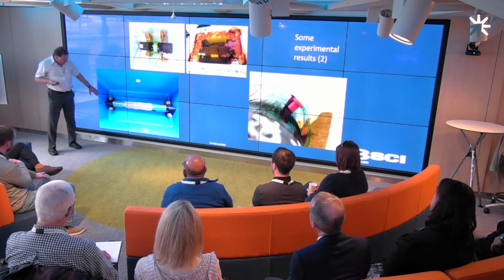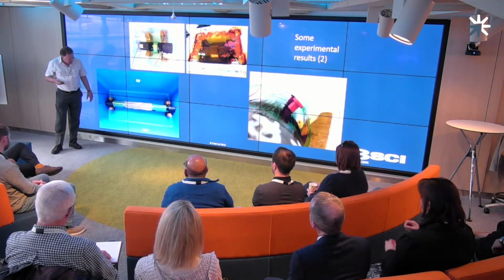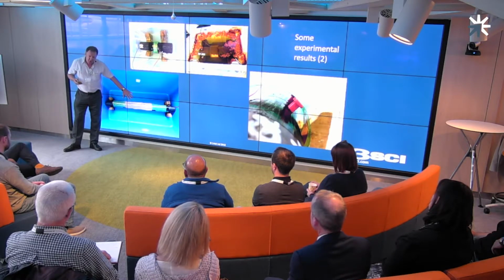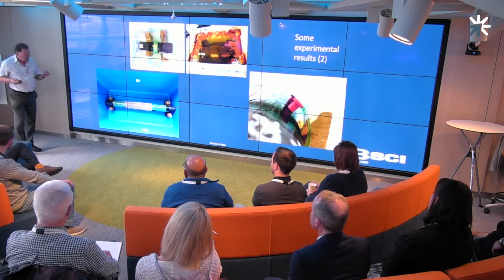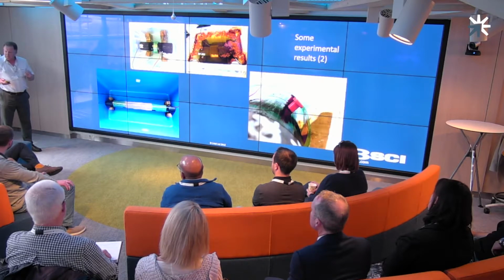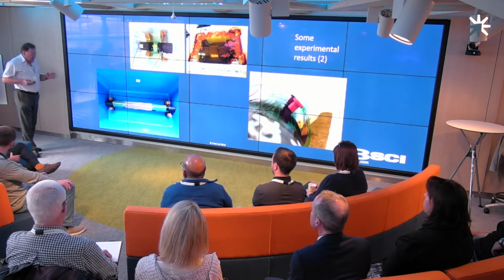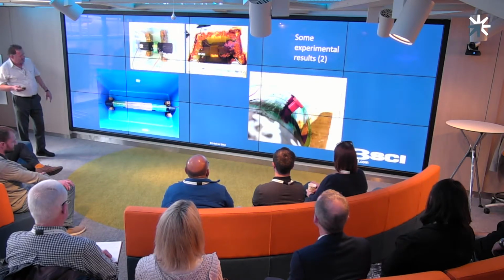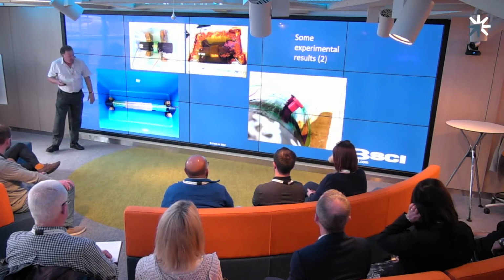And again, just to give you some idea of the additional work we've been doing recently, here's a steel pipe again, sitting in a rather larger tank, with a copper cathode in the form of a mesh placed in close proximity to the steel. We like to choose meshes for the cathode in some of the work we've been doing so far, for a reason which I'll explain to you in a moment, associated with the gas which is generated in the accelerated corrosion process. And a copper mesh is a nice way of getting the area of the copper quite high, and in particular dealing with the gases which are created. And the image down in the bottom right-hand corner there gives you a different view on this image here, where you can see what the standoff is between the cathode and the steel pipe.